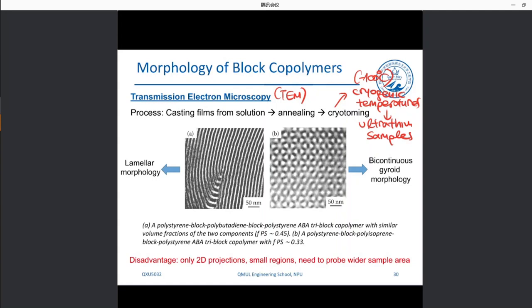Anyway, I don't have too much time before we finish. So yes, indeed, my pronunciation is terrible, apologies for that. To limit vibration of atoms, essentially, what does that mean? It means that we want to go as far away as possible from the glass transition temperature. We want to have the chains completely frozen. By freezing the chains completely, we avoid damage or any distortion of this nanoscale morphology during cutting. So that's why we use these cryogenic temperatures.